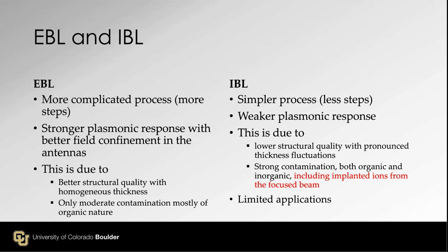Even though there are some issues still there of helium implantation, and xenon is also a noble gas, so it's less contamination issue. However, xenon plasma also can change the surface properties. Not so much with contamination, but can damage the crystal structure. So there are good things and bad things for both cases, but when you wanna make devices, you have to think, okay, which method do you wanna use?